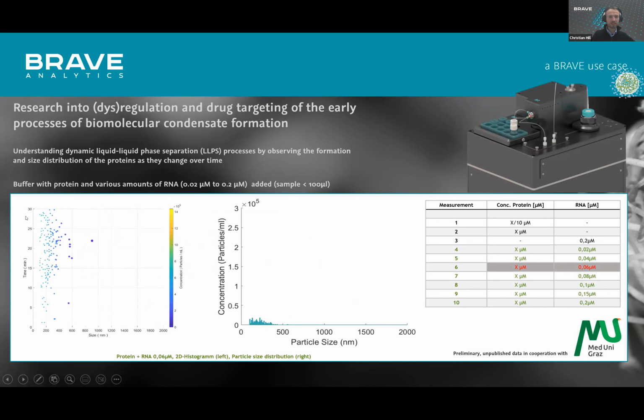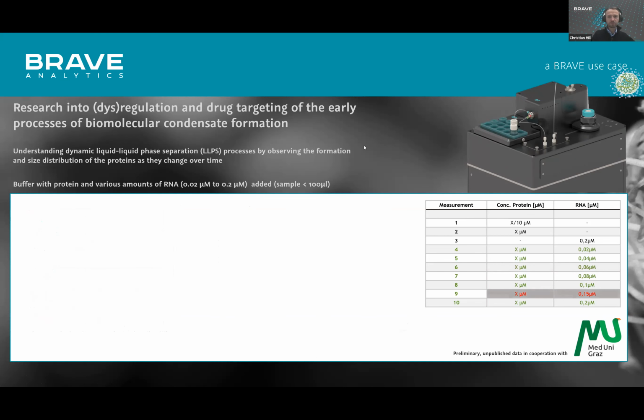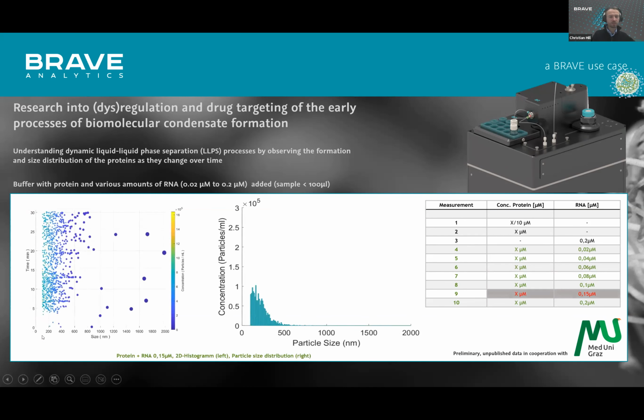And you can see here again time over size, and here on the color bar concentration, that after a while particles are forming, and we can really see them on counting based method, being here roughly 10 to the power of 5 particles each point. And when you go further and you put more RNA, for example, you see that after 5 minutes you really see a concentration and particles form.